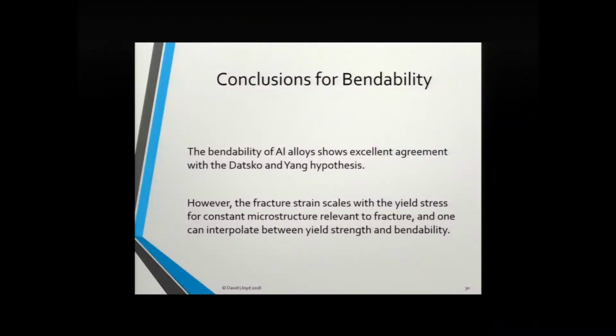So the conclusions for bendability are the bendability of aluminum alloys, and it's not just sixes, incidentally. I mean, we haven't looked at an aluminum alloy that hasn't given agreement with that expression. And it's reasonable, right? Essentially, if you achieve a strain at the bend surface that's equivalent to the fracture strain of the material, it's going to fail. That's the way it is.